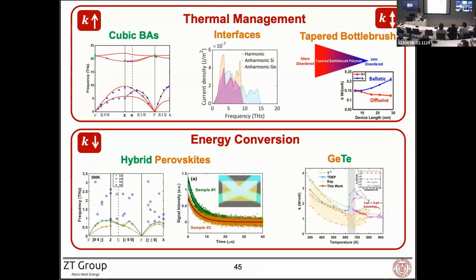Certainly there is a limitation in terms of including the anharmonicity of the leads in the framework, because we just don't see a very clear path forward to include that into this framework. And in terms of if you just do this supercell, maybe creating the superlattices, and then you do the thermal conductivity calculation, I would say there could be two potential concerns.